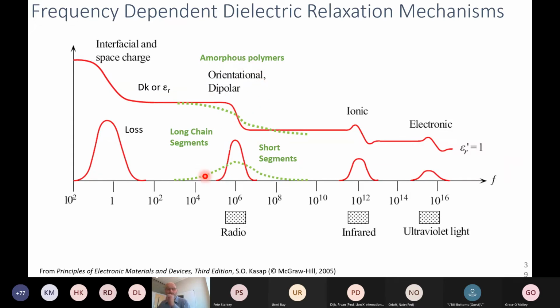So I did show you a peak in the dipolar response for that material. And it's not as clean as what's shown here in the red line. Typically, because these polymers are semi-crystalline, they're not really that uniform in terms of their molecular makeup. Essentially, we don't get a very, very nice sharp peak, but we get some sort of distribution of relaxation modes. And a lot of times those tails will come up into the microwave and millimeter wave.